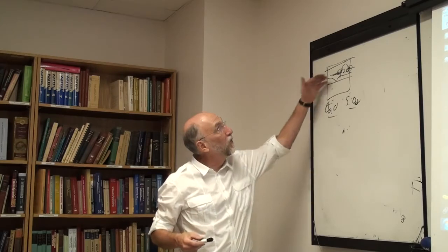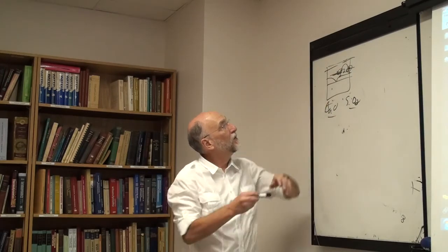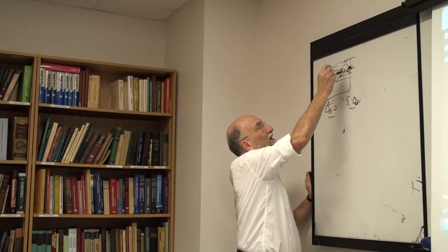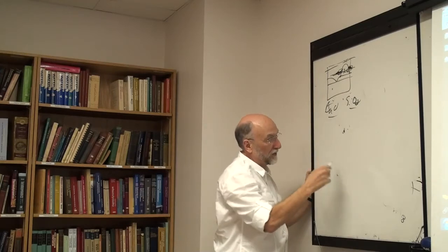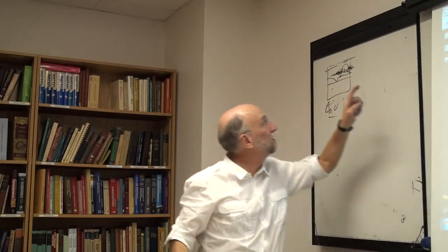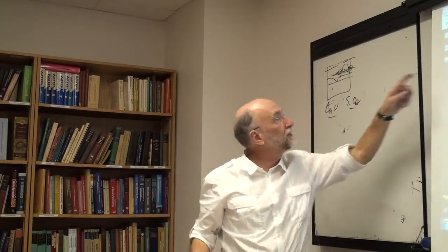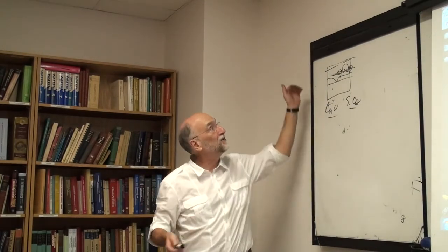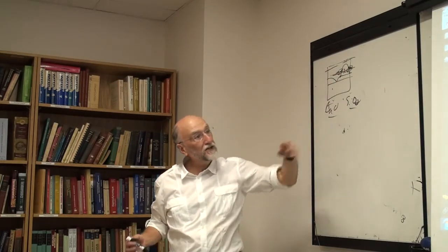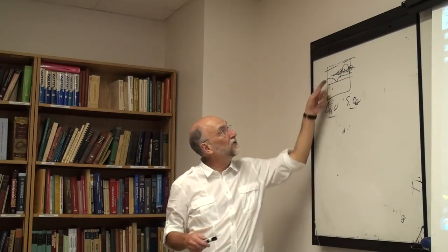You're forcing yourself to have one expansion over the entire composition region. Whereas actually, over a region down here where you have a limiting region here and a limiting region here, each of these regions is much more easily fitted with two expansions. You can probably fit this region with two coefficients, and this region with two coefficients. But to try to fit the whole thing at all compositions requires many, many coefficients, and is much more difficult. Now, you can't get around it, you sort of have to do that. But nevertheless, you have many systems in which you have one terminal region which really does have one structure. You have another terminal region which really does have a very different structure, and there's only a region in between where the two structures join up.